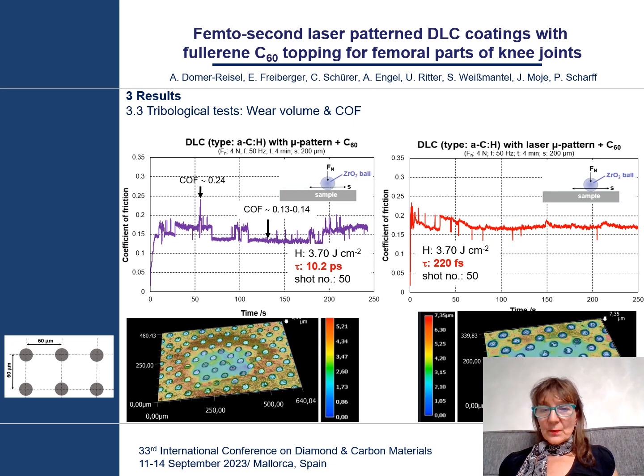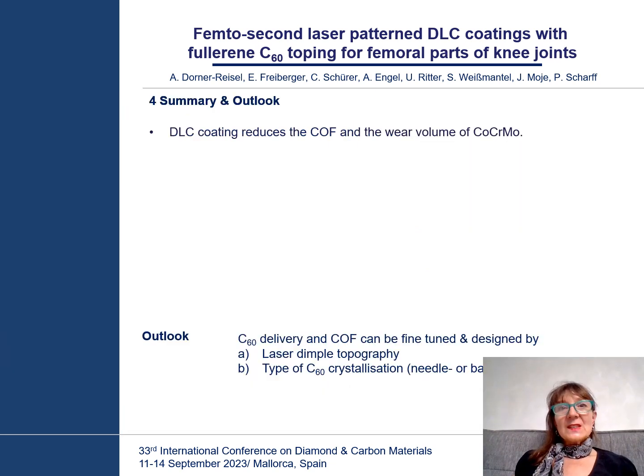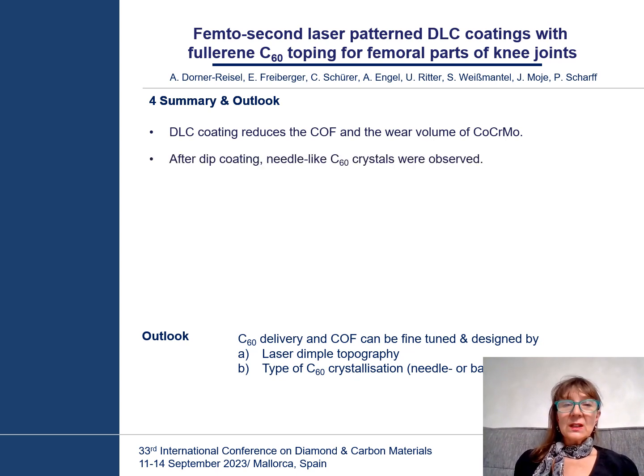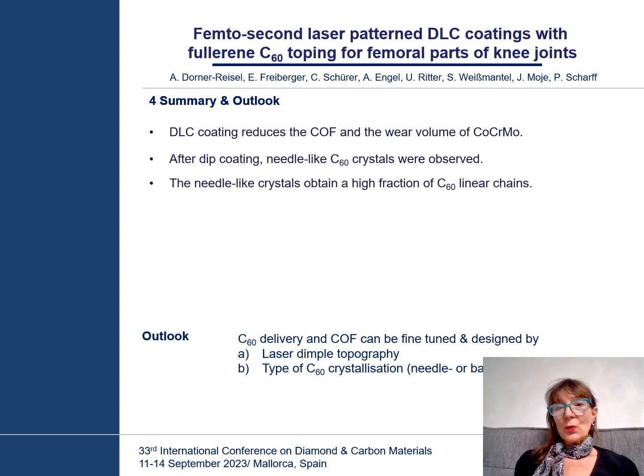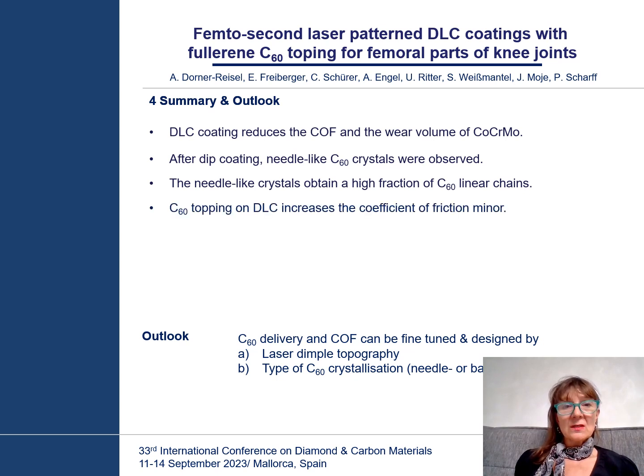I would like to summarize our presentation in the next slide. Summary and outlook. We have shown again that suitable DLC coating can reduce the coefficient of friction and wear volume in comparison to cobalt, chromium, molybdenum. After dip coating, needle-like C60 crystals were observed, and the needle-like crystals obtain a high fraction of C60 linear chains. C60 topping on DLC increases the COF minorly.